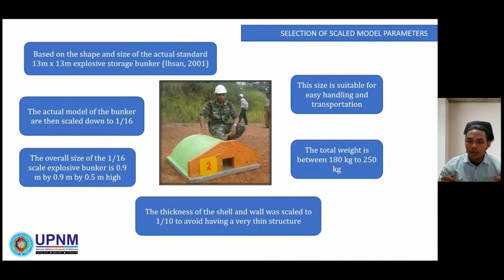We selected a 1/16 scale model. The overall size of the 1/16 scale explosive bunker is 0.9 meter by 0.9 meter and 0.5 meter high. This size is suitable for easy handling and transportation. The total weight is between 180 kg to 250 kg. However, the thickness of the shell and wall was scaled to 1/10 to avoid having a very thin structure. Features like the front and rear vent and steel door openings are provided so that the blast simulates the real behavior of a storage bunker.